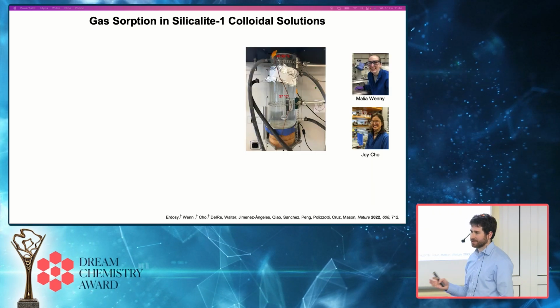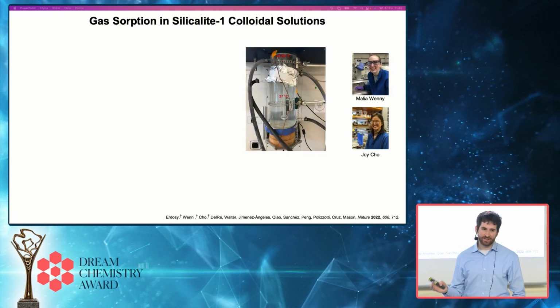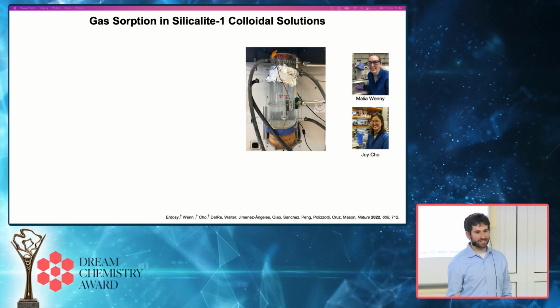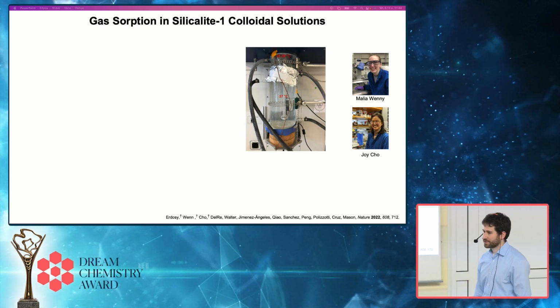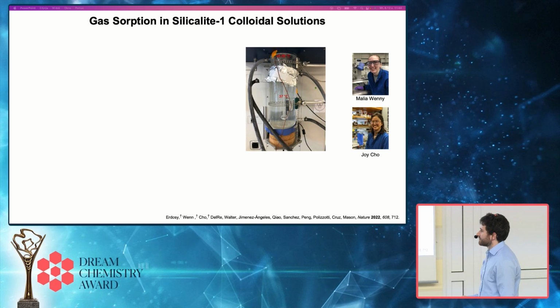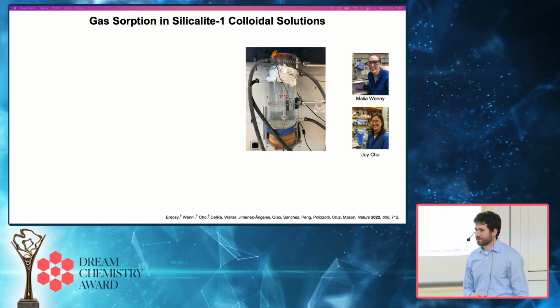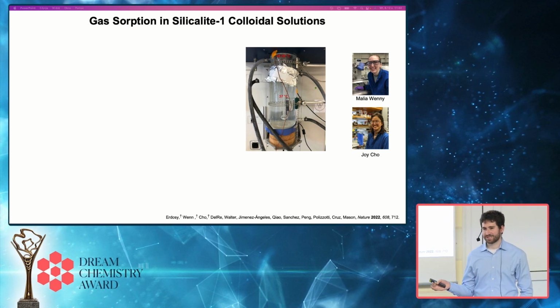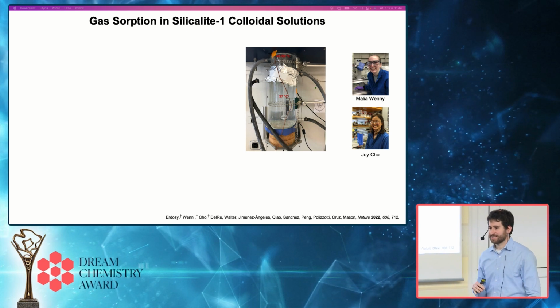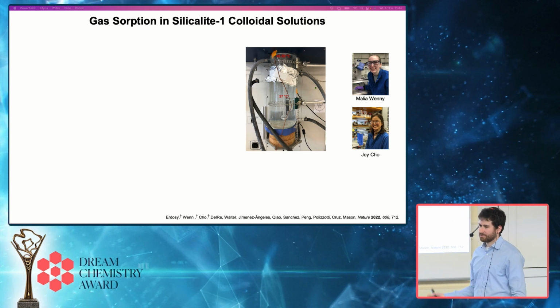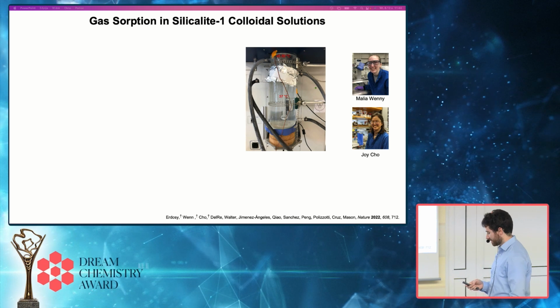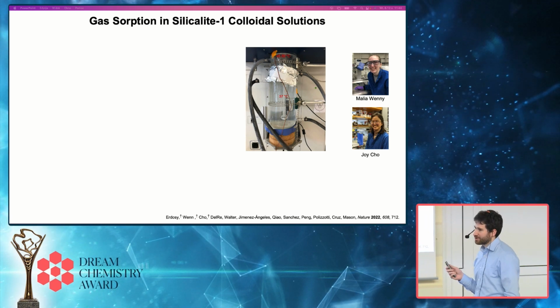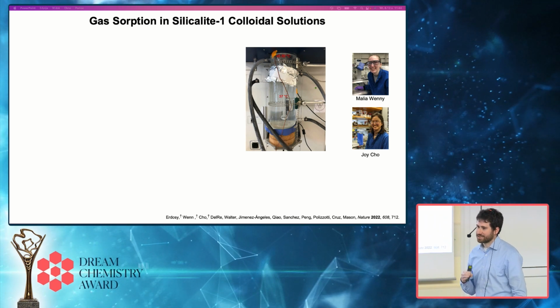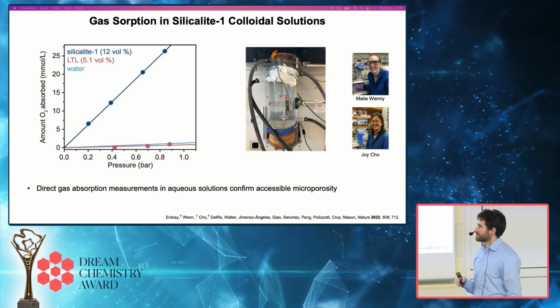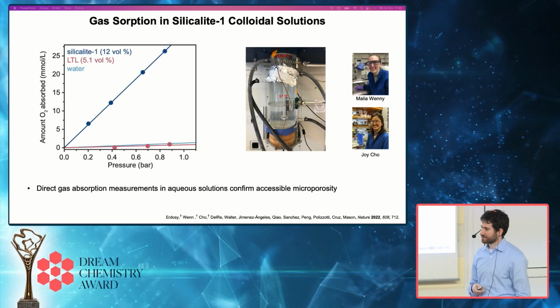So the next question was, are they accessible to gas molecules? And can they remain dry even when we degas the solutions and put them under vacuum? So 2 other graduate students, Malia and Joy, in my group spent a lot of time working out how to do direct measurements of gas uptake in these degassed colloidal dispersions. So we put them under vacuum, we remove all the gas from the dispersion, and then we expose the solution to gas at different pressures, and we directly measure how much gas is absorbed within the solution.